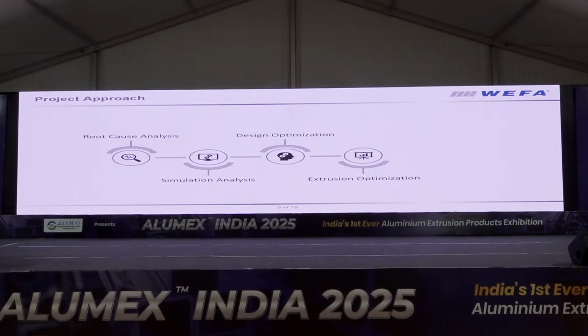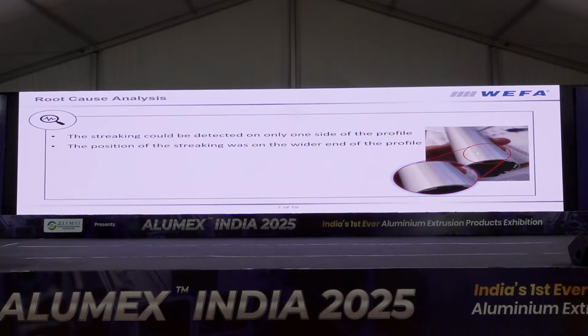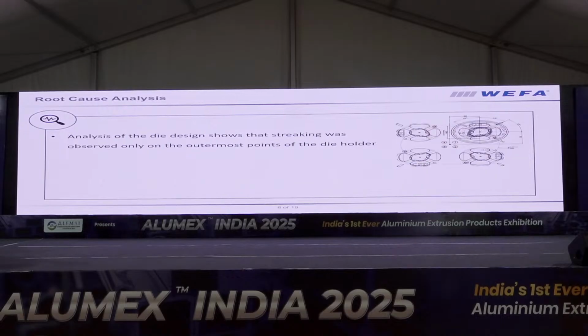So I had to do a root cause analysis. The project approach was to simulate afterwards using the simulation software, then design optimization, then extrusion optimization, and a practical application after. So what was the root cause? We found that the streaking could be detected only on one side of the profile. It was always the outer parts of the profile, and the position was on the outer parts of all 4 cartridges. So it was only here, here, here, and here.